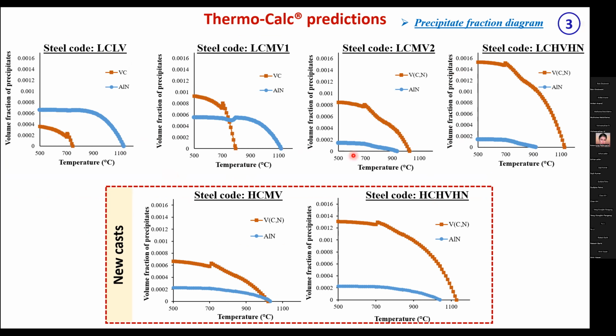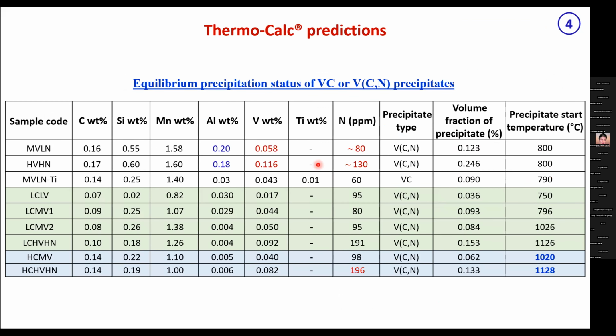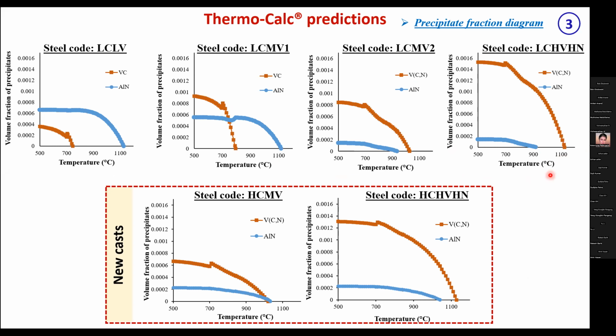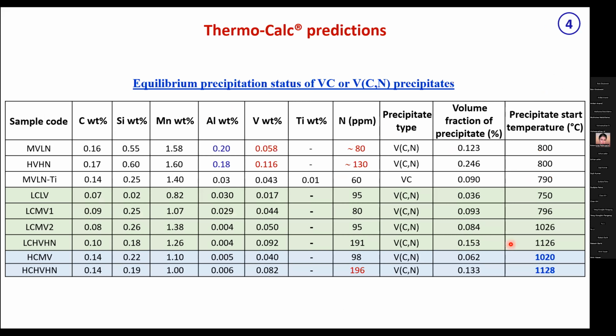So these are the Thermo-Calc predictions. So naturally the steels where we have added more vanadium and nitrogen, naturally the precipitation temperature has gone up to about 1100 degrees and like that. Going to the next slide, if you see here, the precipitate temperature and precipitate fraction we are showing, mostly vanadium carbonitride precipitates that we are expecting. These two I have marked in blue because in the presentation that I shared with Dr. Dev a few days back, these calculations were wrong, because we had set these temperatures a bit high, so zero values came. So these are the actual precipitation start temperatures for this grade, 1020 and 1128. Still 1128 may be considered a bit on the higher side for this high carbon, high vanadium, high nitrogen steel.